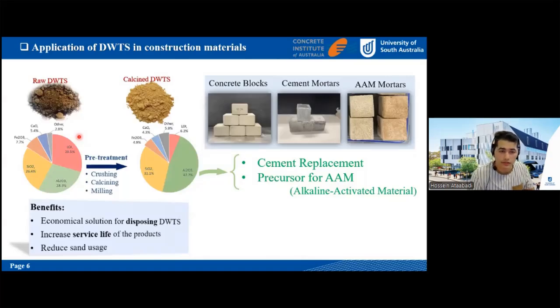However, because the raw sludge has a lot of organic material, around 29%, before using the sludge in cementitious material it needs some sort of pre-treatment. It could be crushing, calcining, or milling. After pre-treatment, you can see that the amount of organic content reduced to 6%, and so the amount of aluminum and silicon increased very sharply. So it can be used in the cement material.